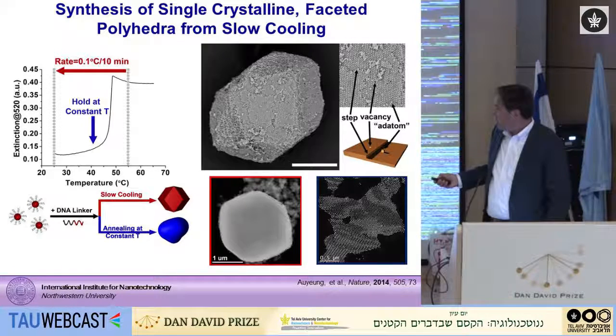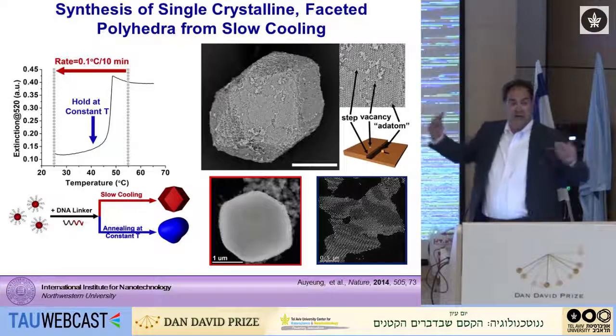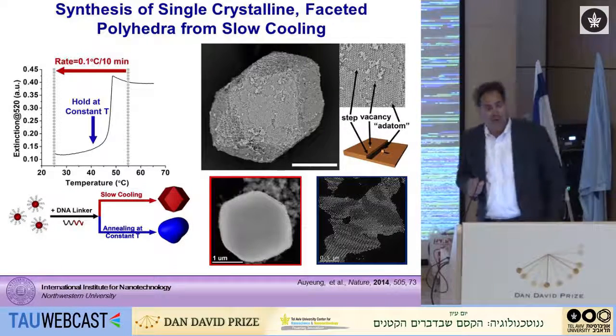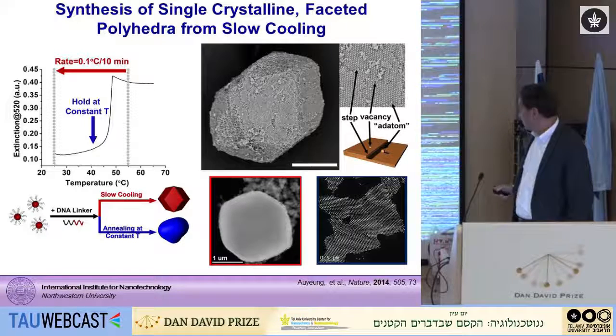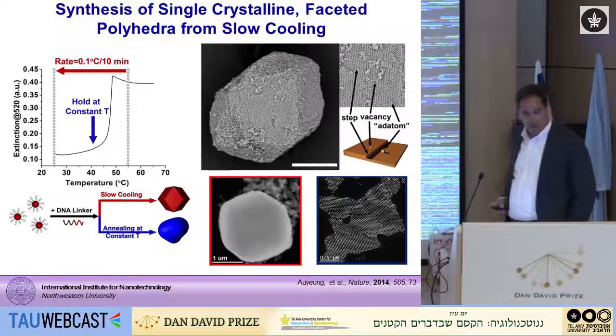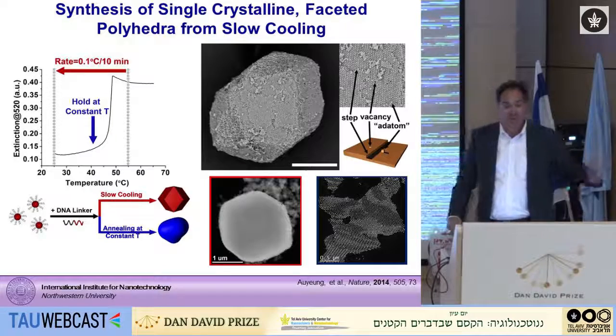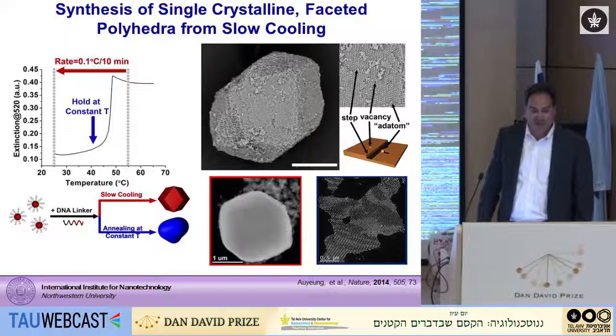And so what we thought was we'd sit here in the melting transition and we could drive defects to the outside of the crystal, kind of the way Paul was talking about it to some extent in the early part of his talk. And what that leads to is greater control. You get higher quality polycrystalline structures, but you don't get single crystals. And then we thought about it.